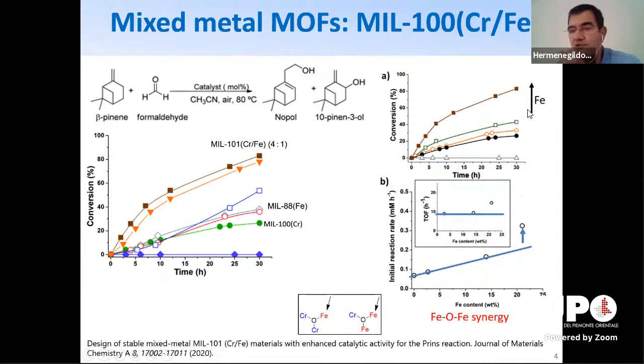So we increased the amount of iron to reach the optimum, and the optimum is at about this ratio, 4 chromium to 1 iron. When you plot the initial reaction rate against the iron content, what we observe is that it was not linear; there was an increase in activity. This increase in activity is very interesting, because it indicates that when you have a cluster, a node, where you have 2 irons, the activity of one iron is increased because the other iron is present. This is a kind of inductive effect in which the higher polarity of iron increases the positive charge on this iron.